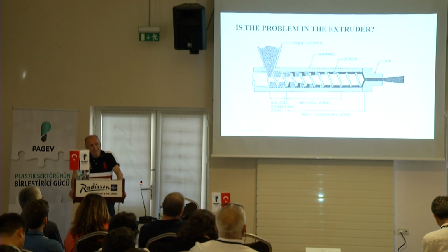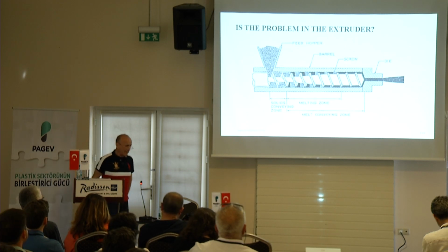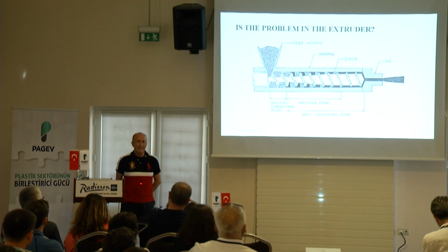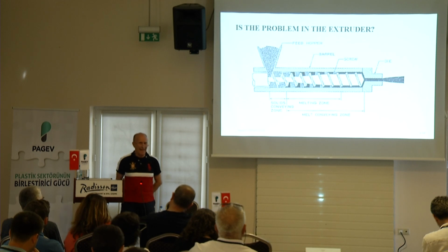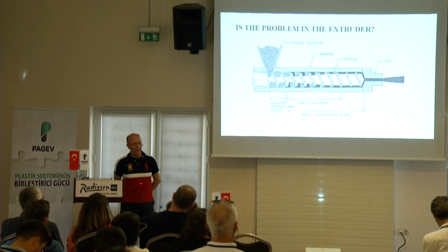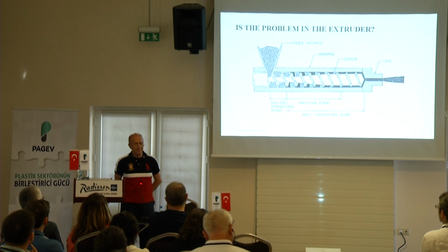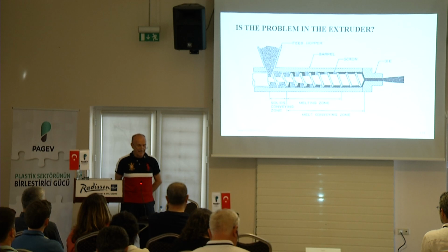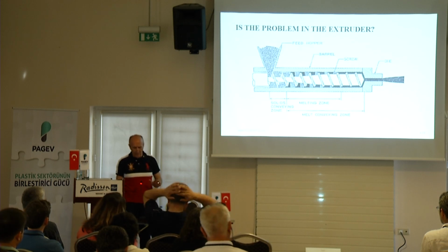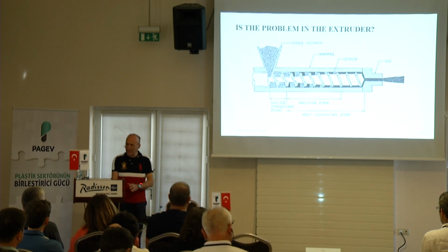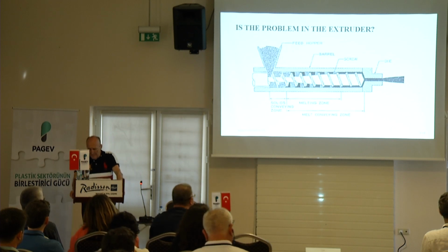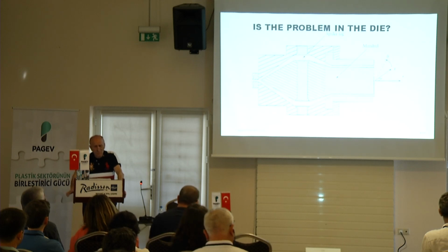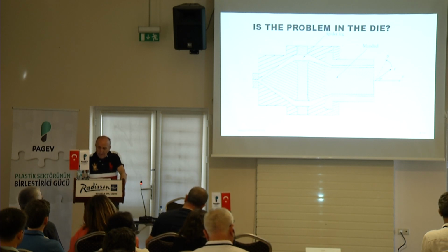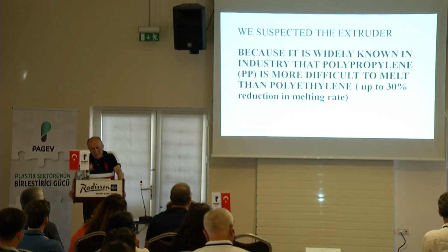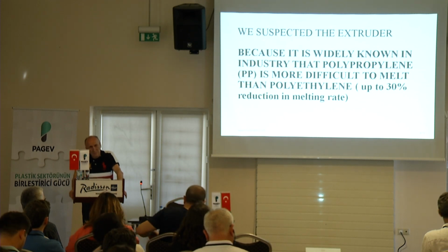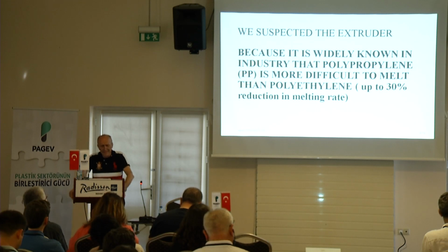Well, I suspected the extruder. Why I suspected the extruder was that polypropylene does not melt as easily as HDPE. I knew that the supplier of the extruder and the screw had a lot of experience with HDPE, and I said, well, maybe these people think that they would use a similar screw design. So I suspected that one. There was nothing unusual in the die. I checked the die. There was nothing there. And so I suspected again that I probably have trouble with the screw design itself,